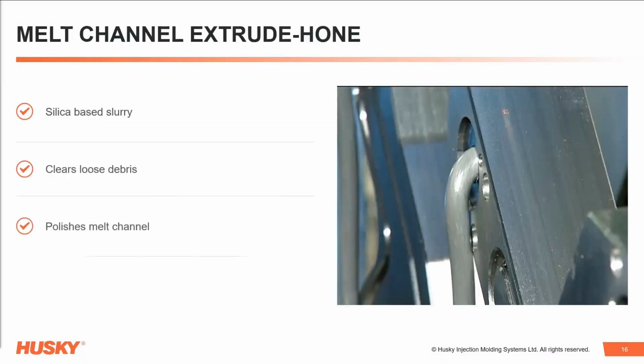Following the resin cleanout, the manifold is extrude honed and washed. A silica-based slurry is injected at high pressure to clear away loose debris, and it polishes any burrs that could remain in the melt channels. If any blockage remains in the channels, it's very easy to recognize it for corrective action.